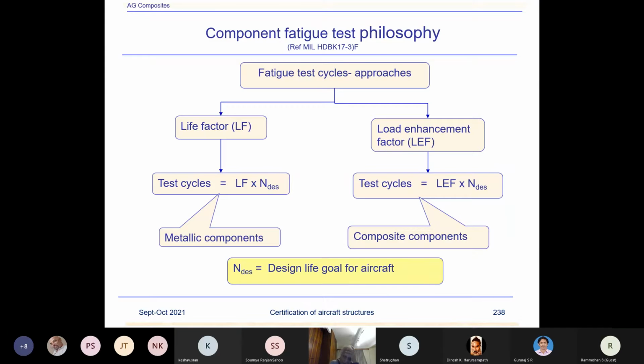There are two approaches which one can use. Life factor approach, where test cycles are LF, which is life factor, into N design. Generally, the metallic structures are tested with this philosophy that you apply a life factor like a 3 or 4 to the number of flights. So suppose you are designing the aircraft for 50,000 flights and you want to validate the life, then apply, say, 4 times 50,000. That means you will test for 200,000 flights and meet the compliance or the fatigue life requirement.